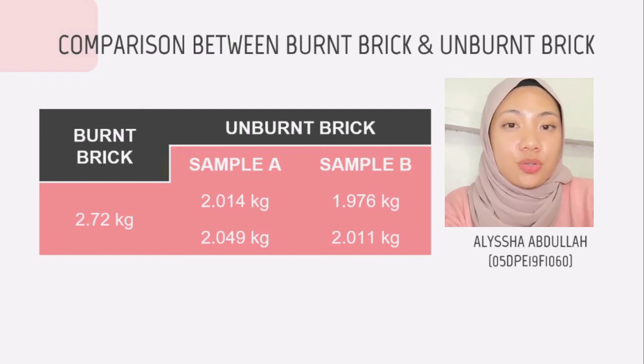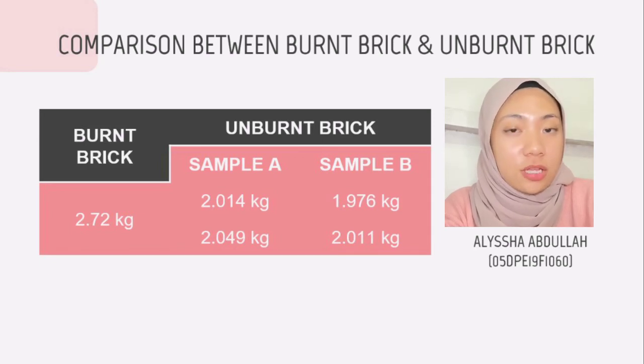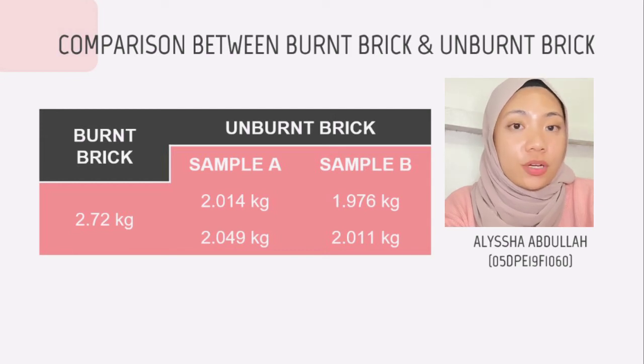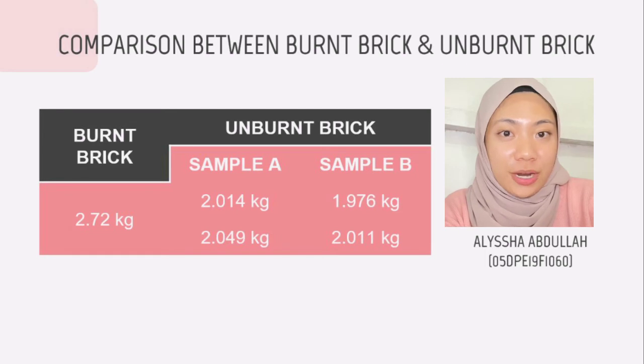As for the burned brick, it is 2.72 kg. For the unburned brick, as a result, sample A is 2.014 kg, sample B 1.976 kg. That is the result for 7 days. Meanwhile, for the 14 days, sample A is 2.049 kg and sample B is 2.011 kg.